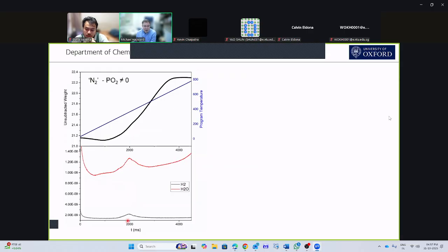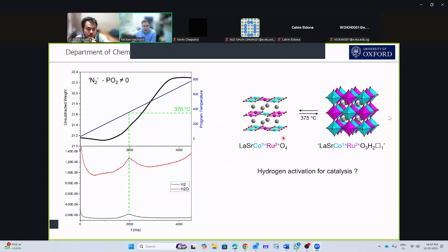So when we heat our system at 375 degrees C, this oxyhydride appears to be in equilibrium with an oxygen deficient phase where it gives off hydrogen, giving an idea that actually maybe we've got something that might be good for hydrogen activation catalysis.